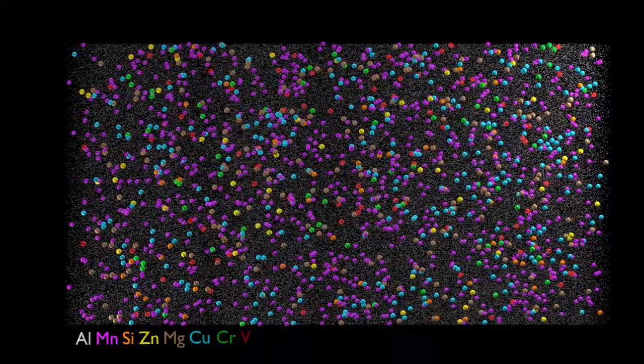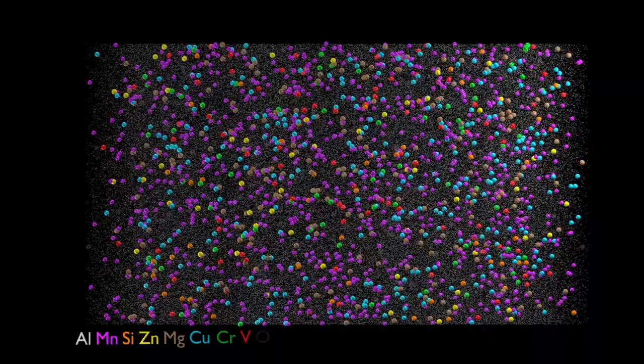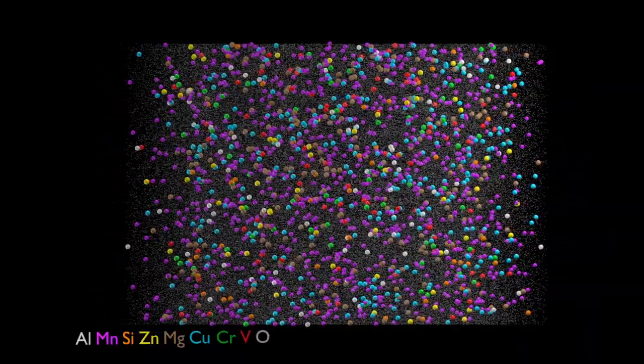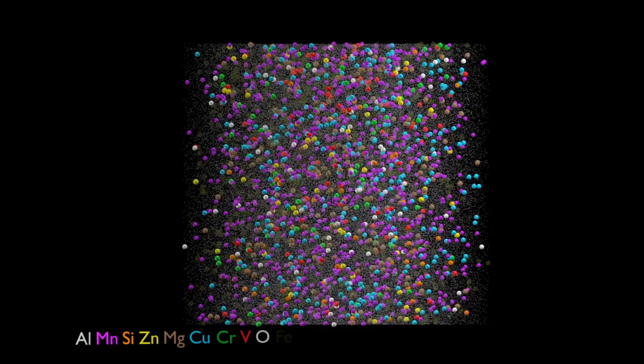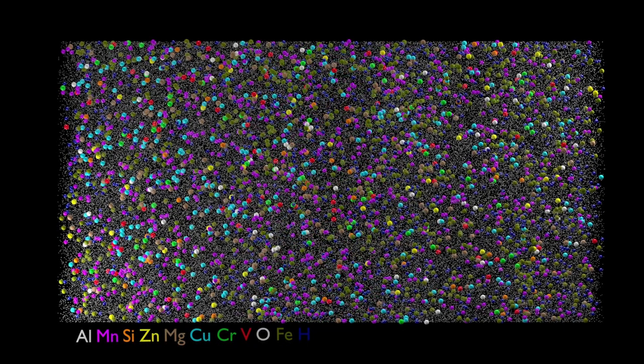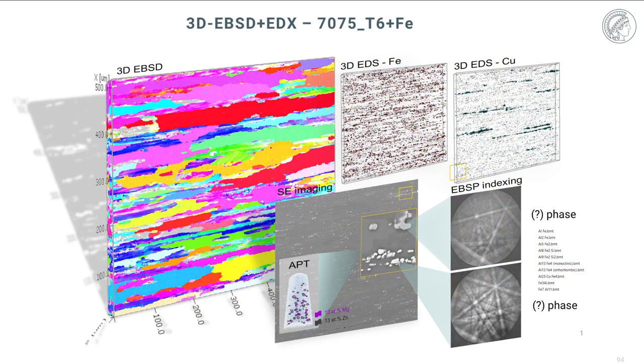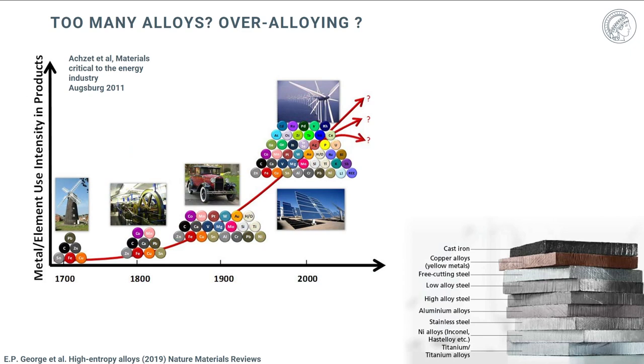But it also shows nicely that a very interesting option for research in the field of aluminium consists in identifying alloys which are more robust against scrap elements as these accumulate over the recycling cycles. So that is, so to say, a science of less pure materials. And of course, in aluminium alloys, particularly the iron is a big problem because it forms also brittle intermetallic phases. And one can, for instance, when you tolerate higher iron content in aluminium alloys, try to change these intermetallics by further alloying in order to make the overall scrap containing alloy more robust